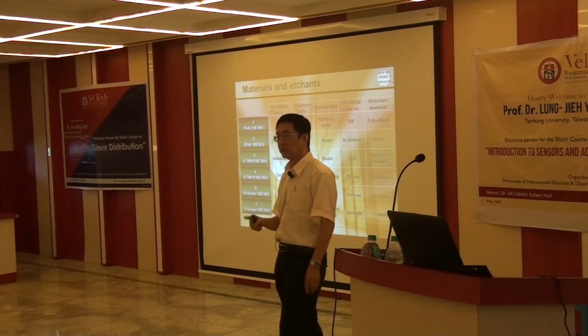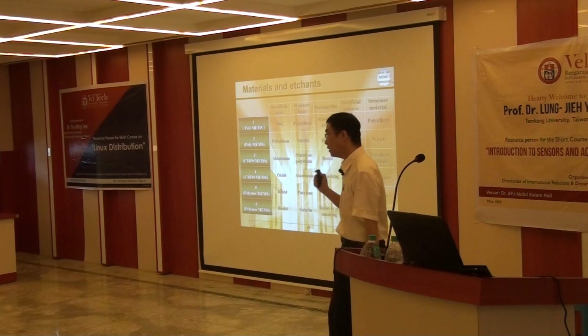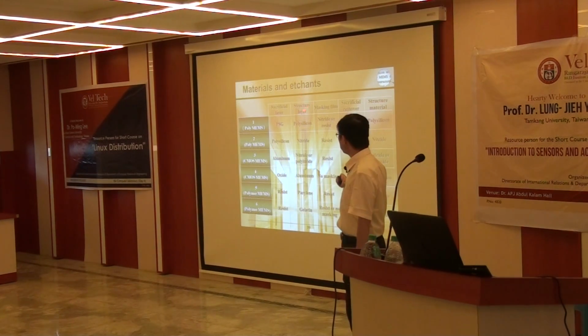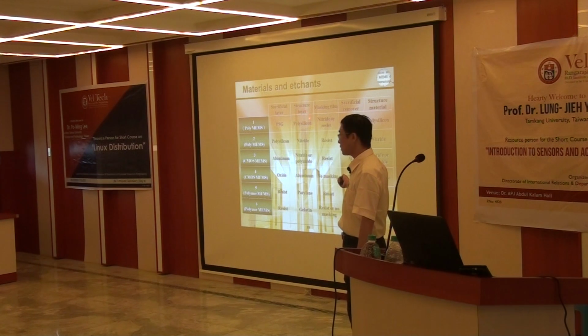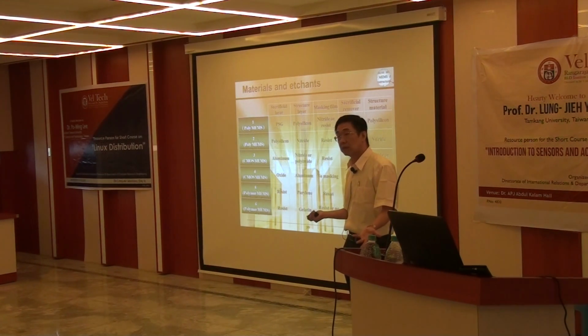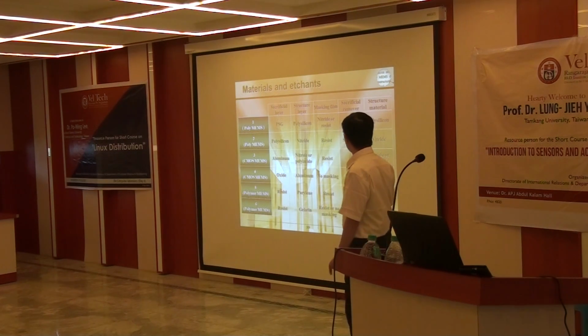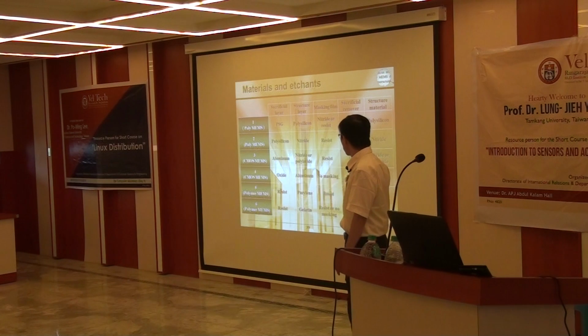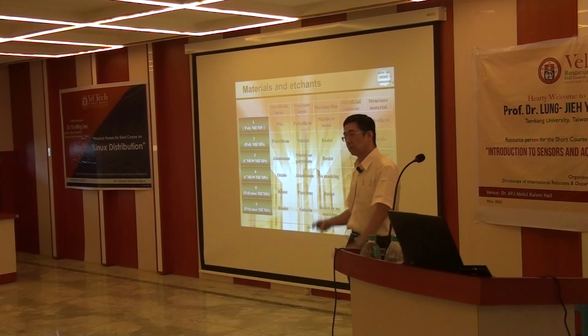So the first condition is satisfied. Second condition, when we finally want to remove the sacrificial layer, will we attack the structure layer? It depends on what etchant solution we use. We use HF, hydrofluoric acid. Hydrofluoric acid can remove glass, no problem. But does it attack polysilicon? No.